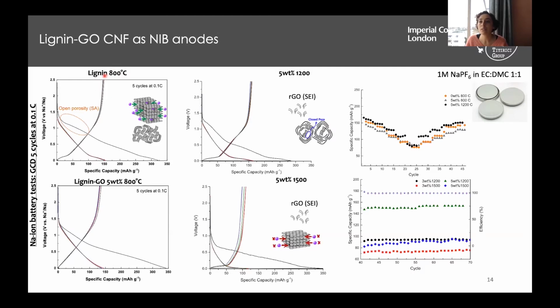For example, when we check the discharge curves of the lignin only carbonized at low temperature, 800 degrees, we can see how we have a very open porosity here that probably is enabling the electrolyte to decompose on top of this carbon. And that's why in the first cycle here, we have a huge capacity that then fades on the second, third, and fourth cycle, as we can see here. At the same time, this capacity that remains is probably due to the enlarged graphene interlayer distances that are still large enough to enable the sodium to go in.